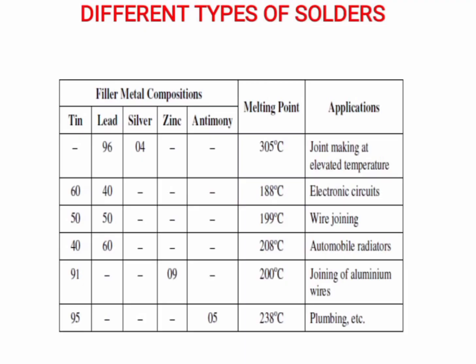Different types of solders are used as filler metal compositions: tin, lead, silver, and zinc-antimony types, with different compositions in percentage. Tin 60 and lead 40 has a melting temperature of 188 degrees centigrade, and is used for electric circuits. Lead 96 and silver 4% have a melting point of 305 degrees centigrade, and are used for joints made at elevated temperature.